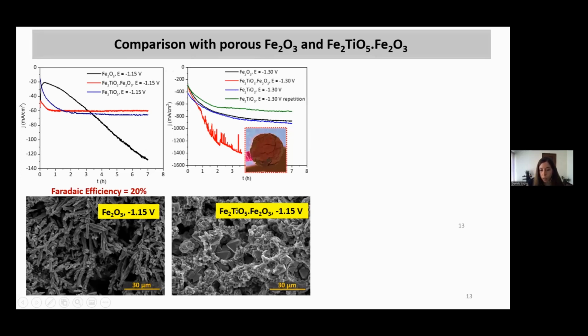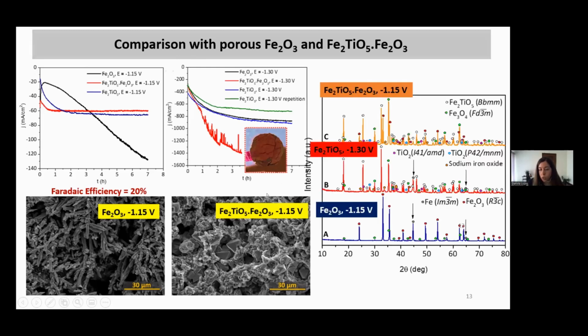So we did the same with the composite. Again, we didn't obtain metallic iron, only magnetite crystals. And when we tried to increase to -1.30 volts, you can see the cathode was destroyed, and this destruction was associated with hydrogen evolution. So only in these two cases, we have metallic iron. We also got metallic iron at -1.30 volts, but with lower efficiency because of hydrogen.